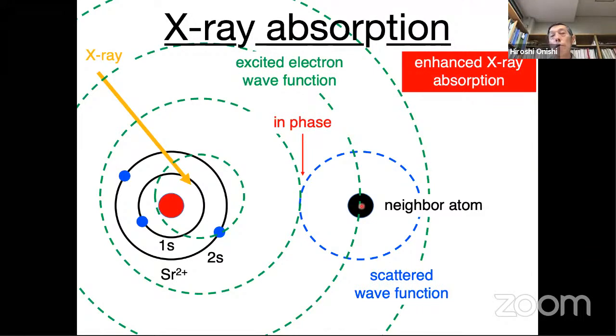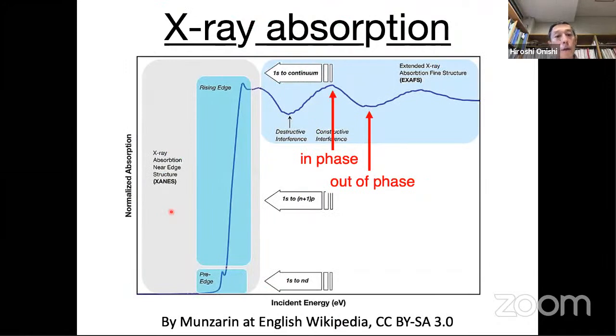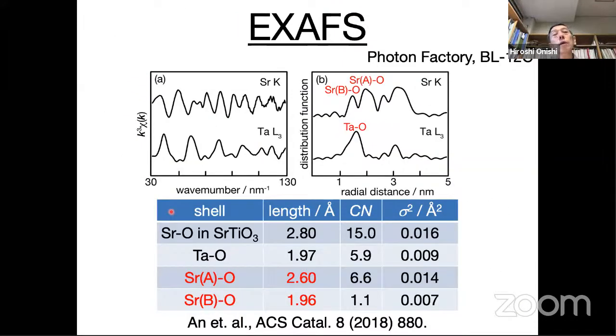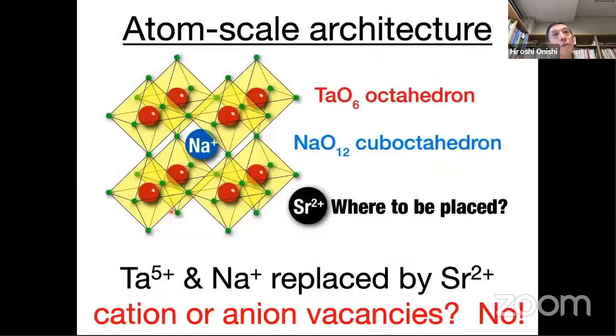So we applied this method to determine where our strontium cations are in the sodium tantalate. As a result, finally, we found that our strontium cation is in the sodium place, and at the same time at the tantalum place. Not just sodium, not just tantalum. Both elements are simultaneously replaced by strontium cations. So this is a result from the X-ray absorption analysis.